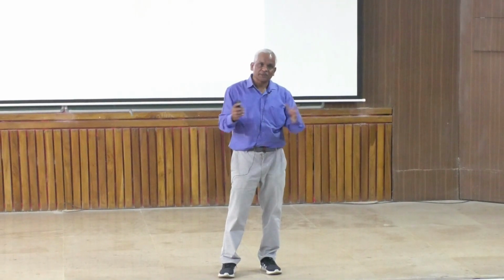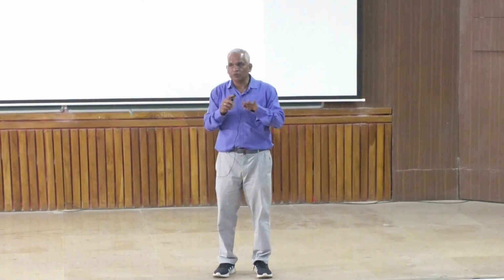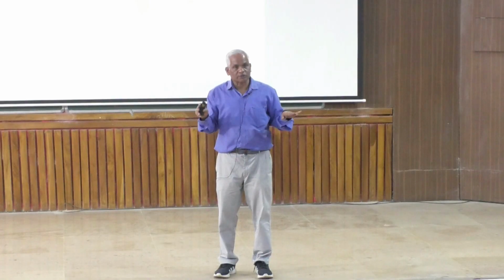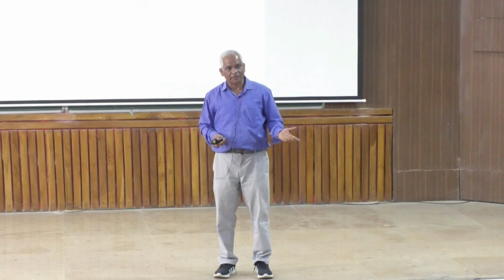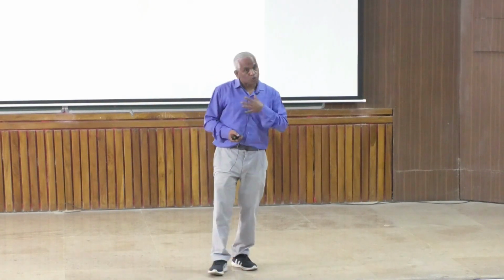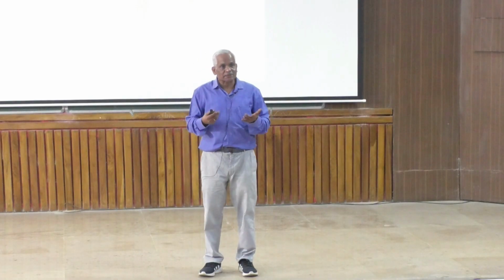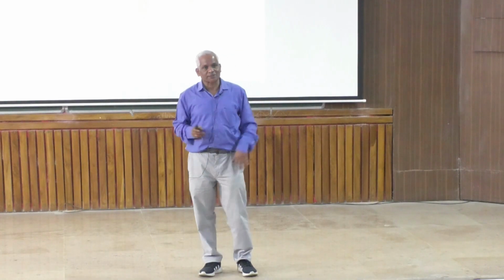Even if you put more, one way is good. Full loading level is not good because electron transport will not be facile. Anyway, you have to get facile electron transport, and only then can you get this reaction. So the low loading level is good, what we got. But why it is happening like that without our control, that we don't understand. And one more question, sir. If the point was written that the window aperture of ZIF-8 is smaller than the Keggin structure, that means the Keggin structure is bigger in size than the ZIF-8 aperture. That's what I'm telling you.